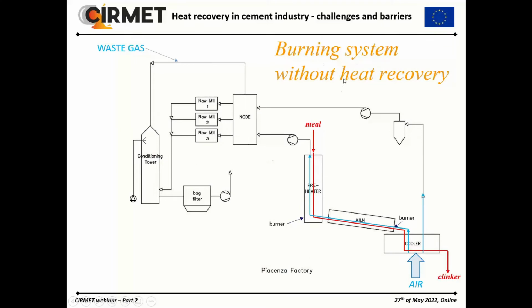In this burning system, we insert meal at the top of the preheater. The meal passes through the kiln, is cooked up to 1400 degrees, and then quickly cooled down in the cooler, in the grate cooler. In this way, we obtain clinker. We cool the clinker by blowing fresh air into the cooler.